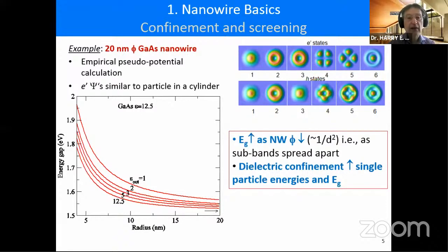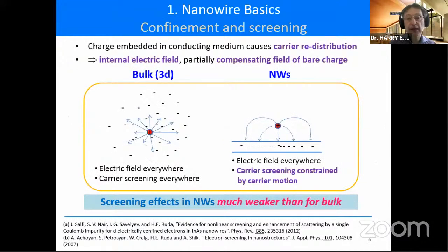But more interestingly, on the left, you'll see that the exterior dielectric constant, that medium, matters. So if, for example, it's in air, then the dielectric contrast between the wire, with its high refractive index or high dielectric constant, and air, causes electric fields to concentrate in the wire, and that raises single particle energies. Call that dielectric confinement, and we're going to see how that can be used very nicely in nanowire structures for things like sensing.